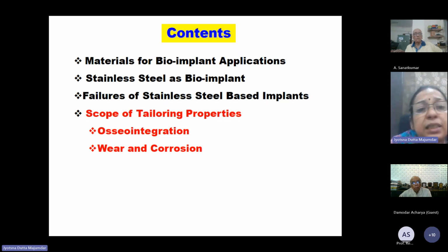Another problem associated with the implant is scar formation at the interface. Particularly when you talk about pure metal without any kind of bioactive coating, if you insert it in a human body, you will find that the typical mechanism of cell or tissue growth is by mechanical anchoring. If the surface is not properly prepared or sensitized, the cells do not grow properly, and as a result there is fibrous tissue growth on the surface, which is again not good for health. Then at the interface between the implant and the tissue, there is cancerous cell growth. So it's not really good for health in the long run. So you have to prepare the surface. Surface preparation is a must.